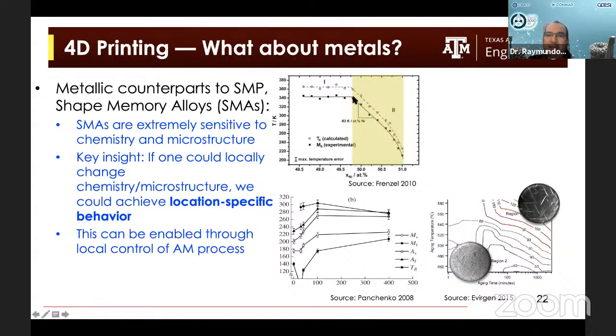And you can see how the transformation temperature changes from 340 Kelvin at close to 50% nickel. And then as soon as you go to 51% nickel, so you have changed the composition by less than 1 atomic percent, the transformation changes by 140 degrees Kelvin, right? So this is an extreme sensitivity to composition.